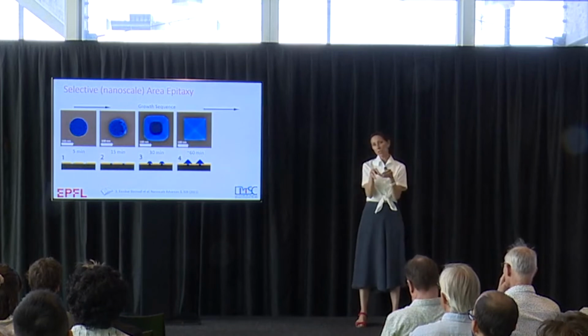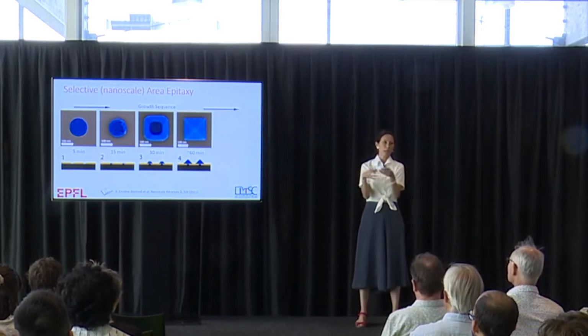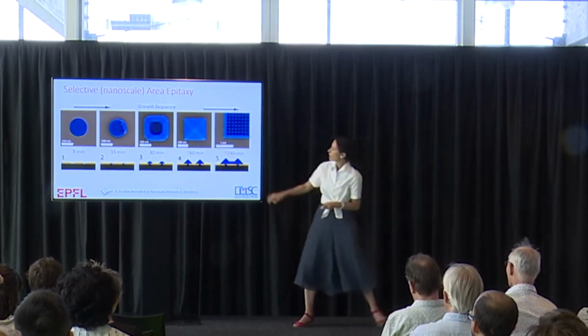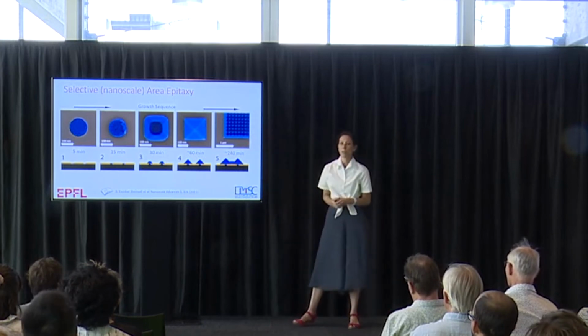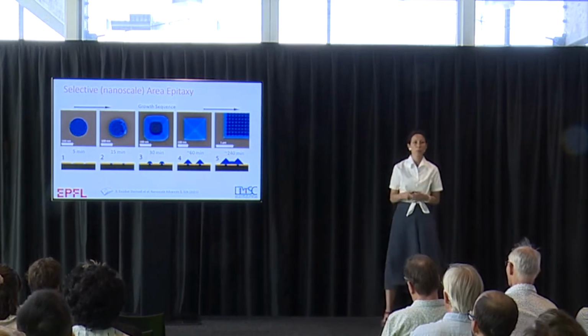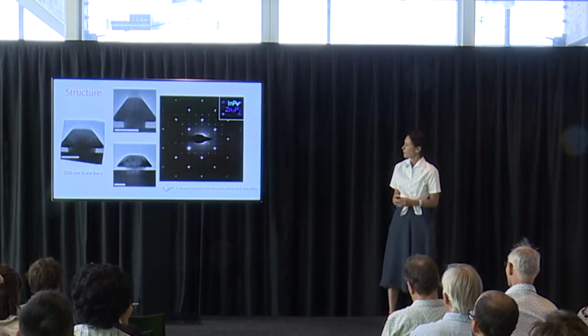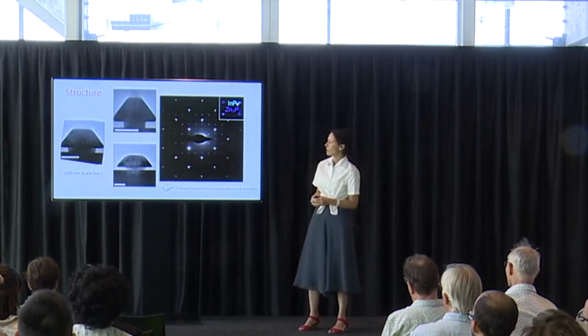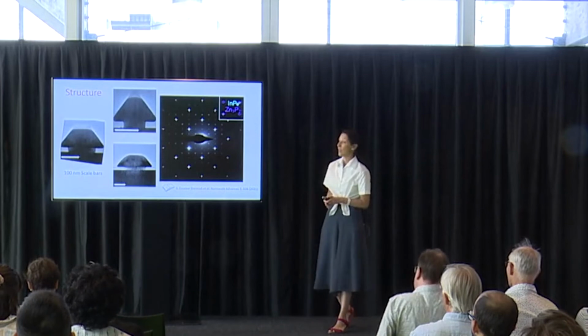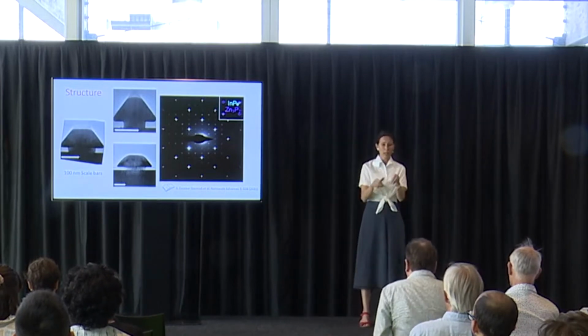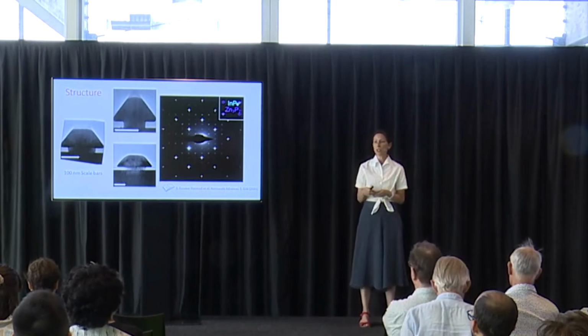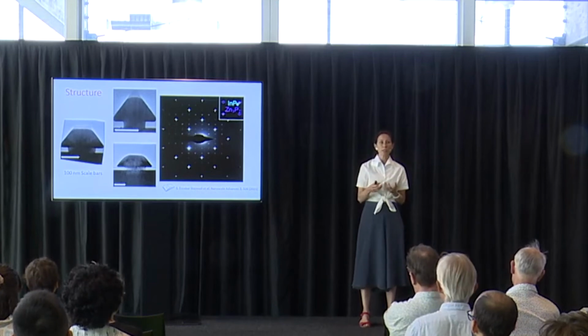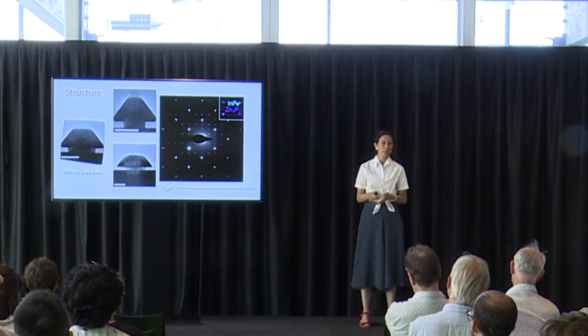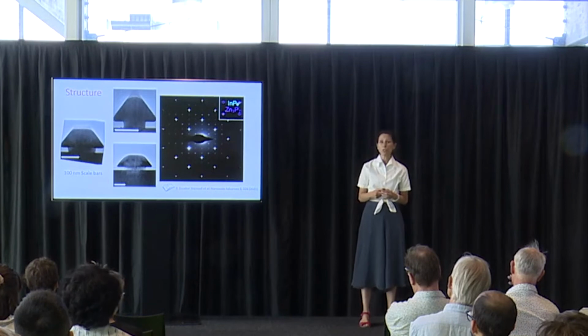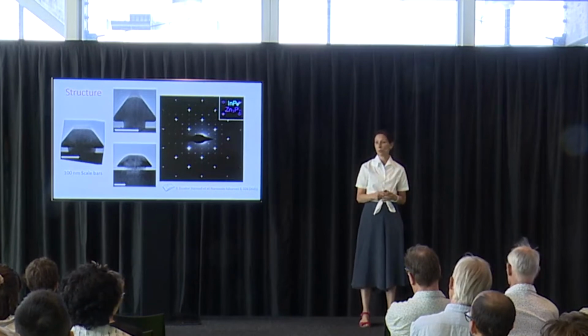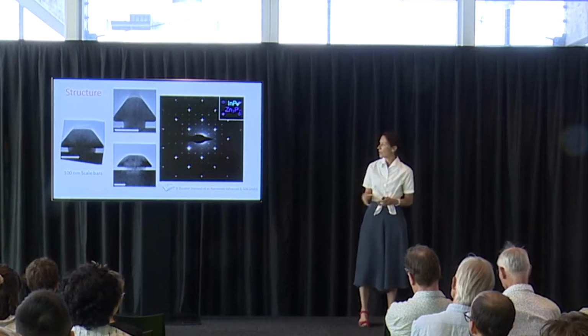Then if these holes are close enough, the pyramids will join, and that's what you see here. You have a highly textured material formed by these pyramids. If we now look at this structure in a cross-section TEM, we see that even though they started from islands that are decorrelated with each other, something happens when they join so that they agree with each other and it creates a single crystalline form. It's quite surprising for me from the epitaxial point of view. I would have never expected this. But they are single crystalline.